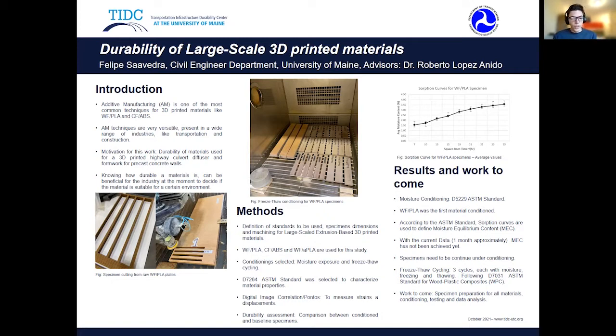Below there's a small figure of how the materials and specimens were obtained. You can look at the lower left. Moving to the next point, talking about method. The first step was the definition of the standards to be used, the specimen dimensions, and machining for large-scale extrusion-based 3D printed materials. One of the challenging parts of this work was obtaining the specimens because they were not 3D printed directly. They were cut from plates and forms from the two projects previously mentioned. So a plan had to be made to move forward with obtaining the specimens.